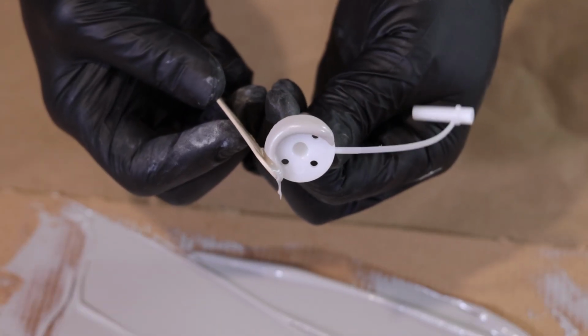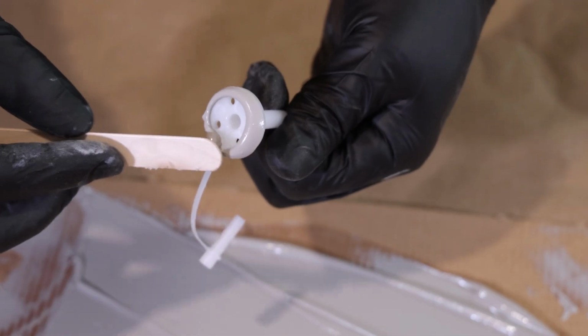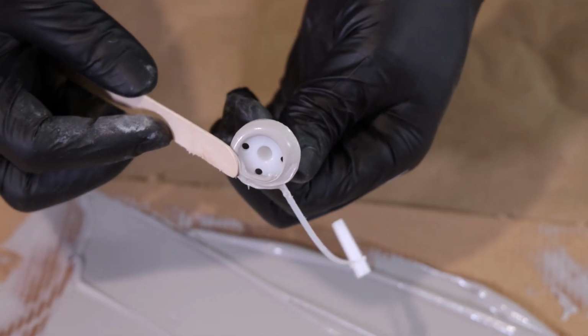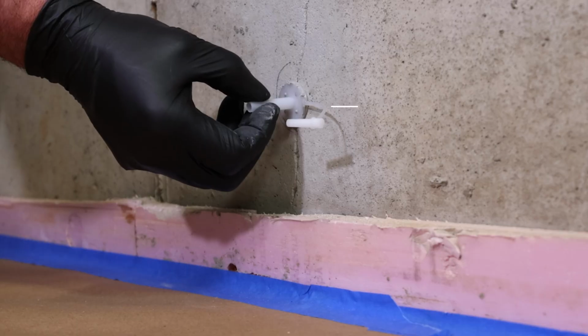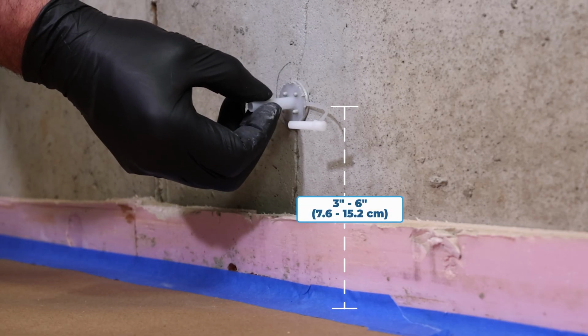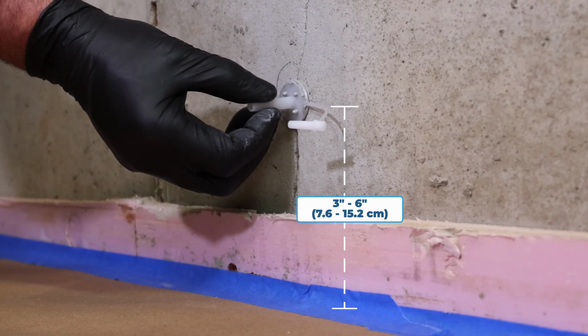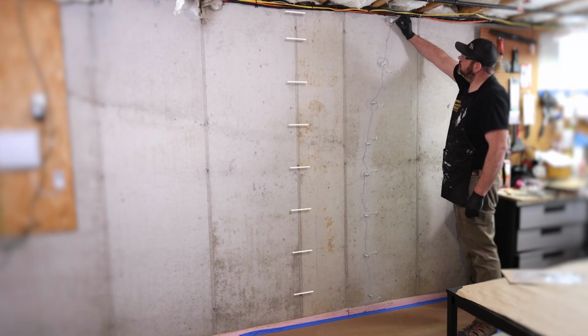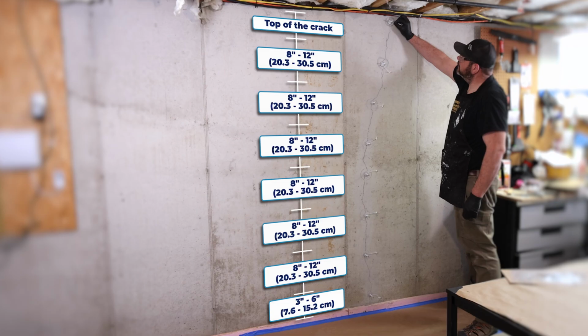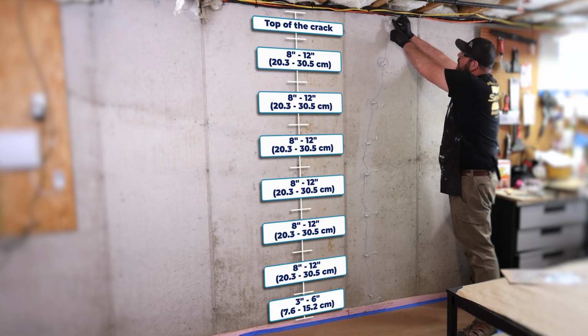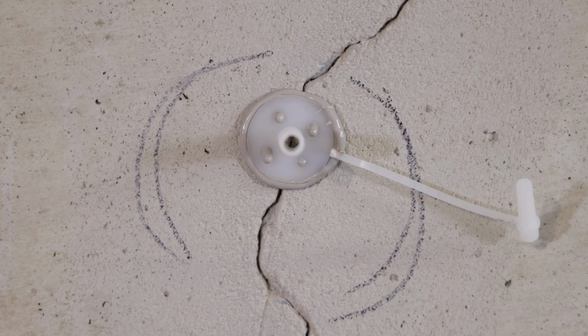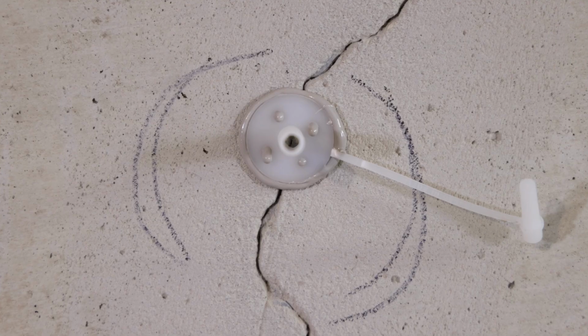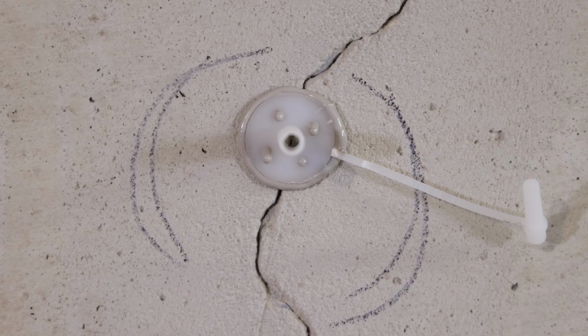Apply a small amount of paste around the edges of each port, being careful not to block the center hole. Align the port directly over the crack and press it firmly into place. Continue this process up the length of the crack and add a final port at the top to confirm resin penetration later. Let the paste tack up for at least 90 minutes or longer in cooler conditions.